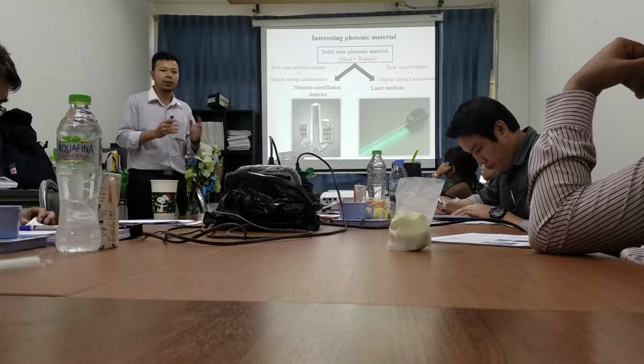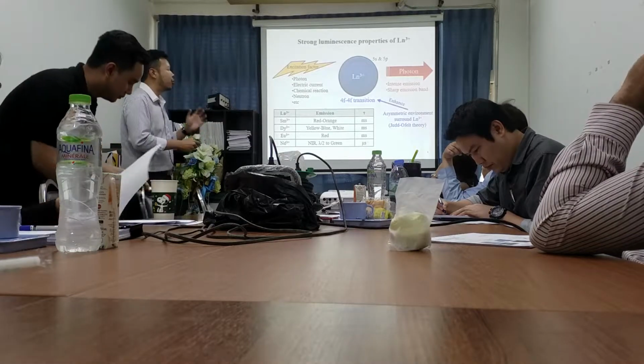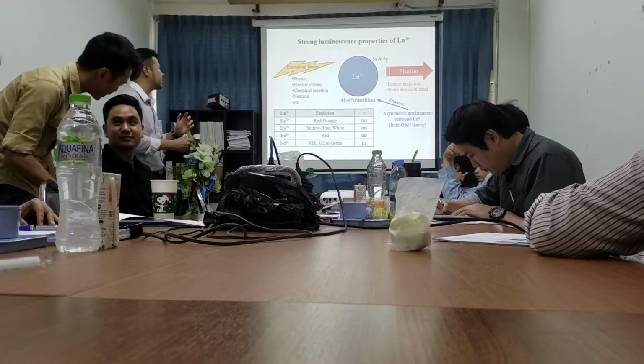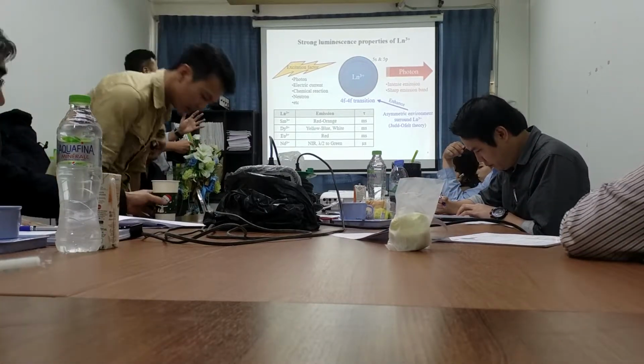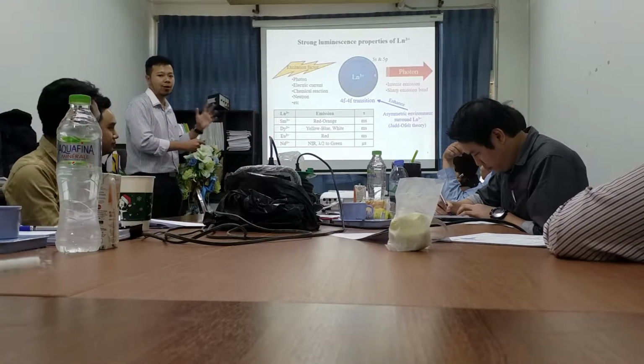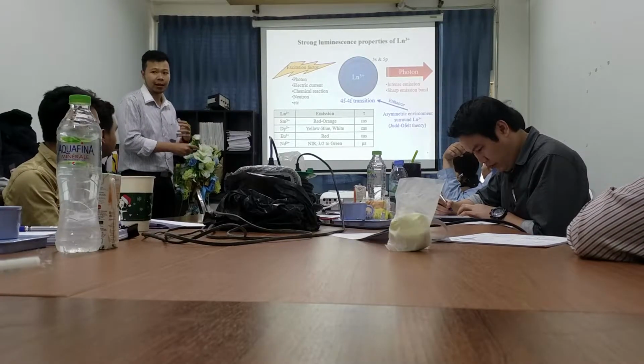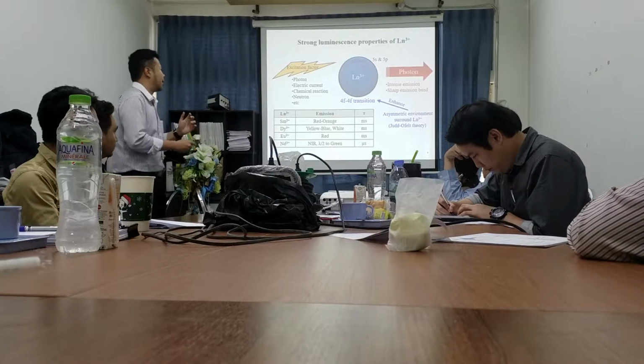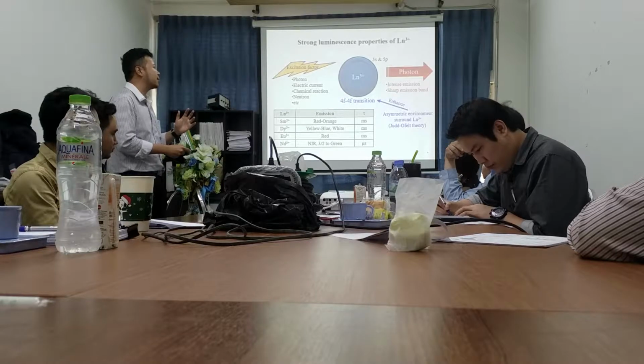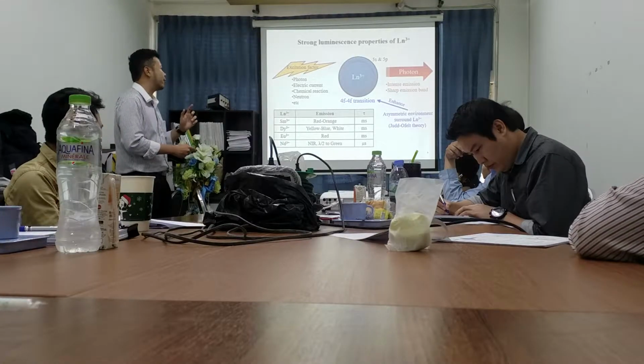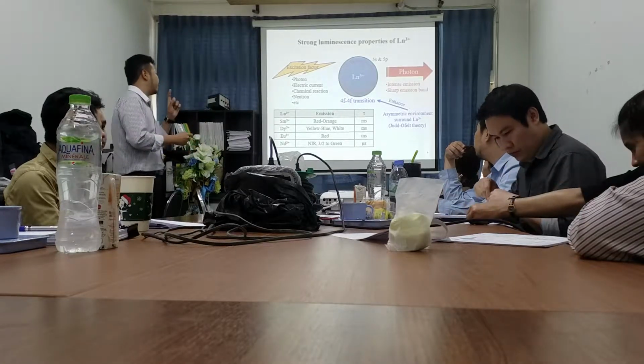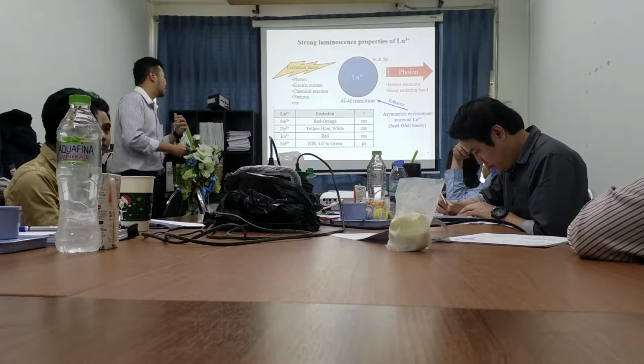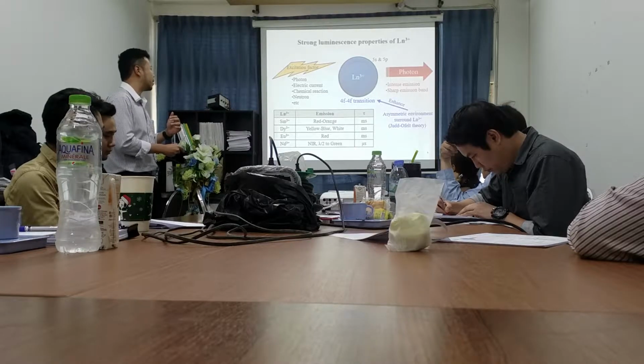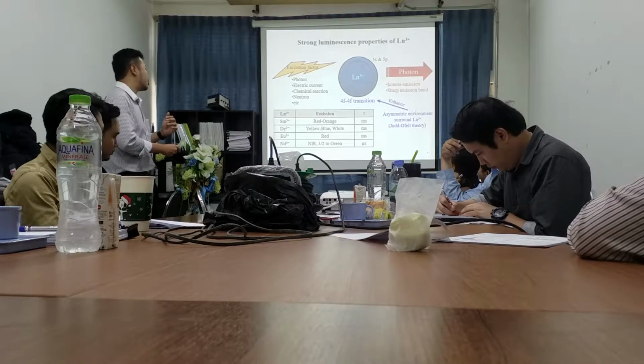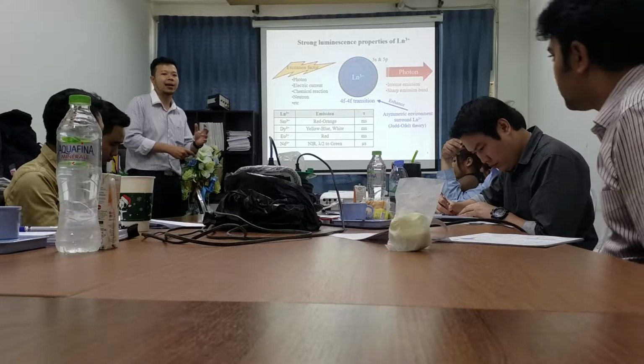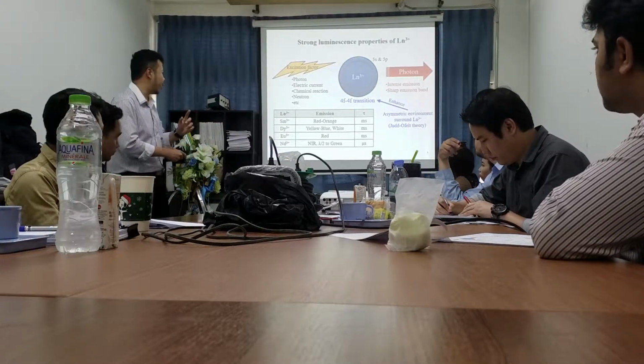Therefore, we need to try out the dopant first, and we choose lanthanide ions as the dopant, because when lanthanide ions are excited by proper energy, such as photon, electric current, or neutron, the f-f transition of the lanthanide ion occurs and gives us strong emission. We can get sharp emission bands from lanthanide ions. And from the Judd-Ofelt theory, an asymmetric environment surrounding the lanthanide ion in the matrix can enhance the f-f transition, giving us the best luminescence of the lanthanide ion. For this thesis, I use four lanthanide ions to dope in my glass. Start with the samarium ion, which shows reddish-orange emission. Dysprosium ion shows yellow, blue, or white emission. Europium ion shows red emission, and neodymium shows strong emission in the NIR, which we can use with a nonlinear optical material to convert to green emission.